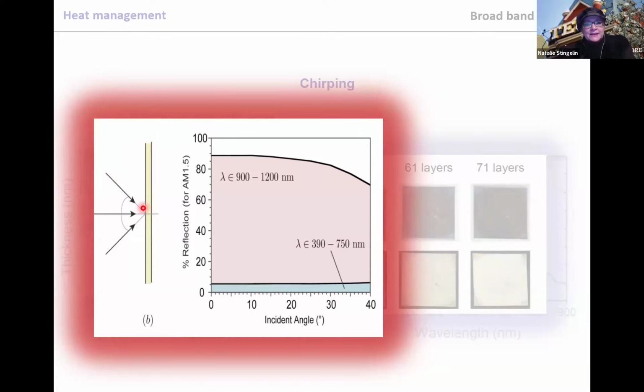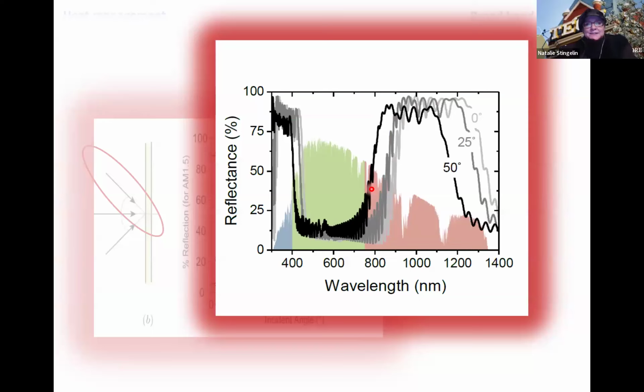I should use this schematic. When you do the chirping, you see we get very high reflection across a broad range of angles. And even at like 35 degrees, you still have considerable reflection. So independent of how your solar cell or window looks like, you reflect the light.